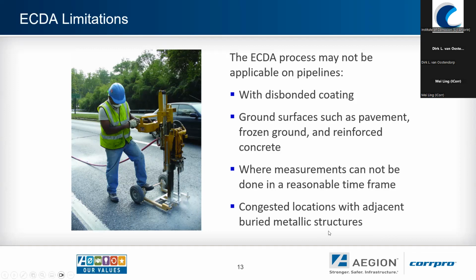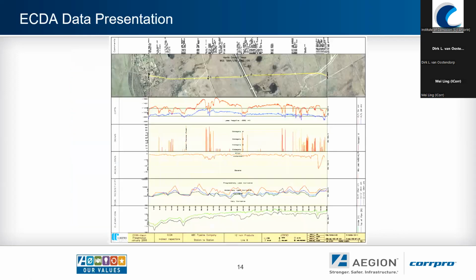And lastly, if there's a great amount of congestion, so for example, in some of the large cities, we suffer as well, where there are pipe type cables, multiple different underground utilities, conduits, duct banks, and all of the other structures. Under those conditions, there may be limitations as far as shielding or data biasing with respect to the external corrosion direct assessment process. So these are all taken into account in the pre-assessment phase when trying to determine if it's feasible and which techniques would apply.